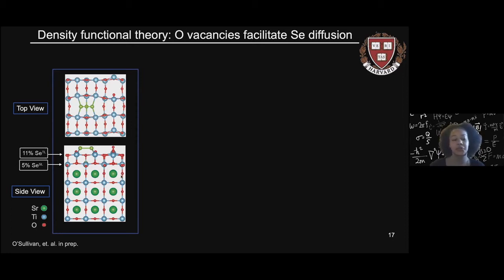selenide crystal once again. However, you'll note in this crystal, we've imposed 11% oxygen vacancies in our top layer of titanium and 5% oxygen vacancies in our second layer of titanium. And in these oxygen vacancies, we've inserted selenium. So these highlighted regions in the top view and the side view are where selenium is replacing oxygen.